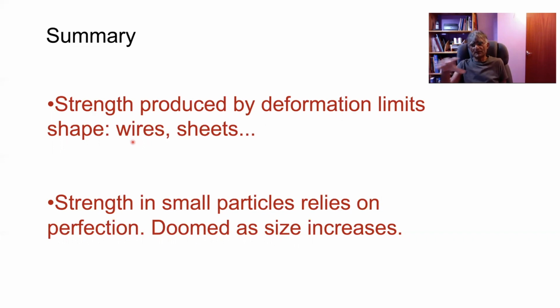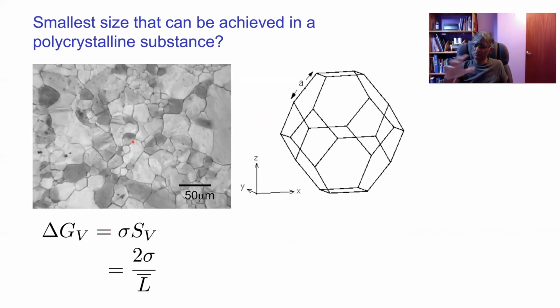Now, there is a process which has been incredibly successful in mass producing steels. It's known as thermomechanical processing, where you have the steel hot deformed in the presence of very small particles of carbides, which limit the growth of the austenite grains, and therefore you can end up with very fine ferrite grains. Okay, so let's see if that process, which definitely is a bulk production process and produces steel samples which are very, very large if you want them to be large, and ask, what is the smallest size that could be produced by thermomechanical processing?